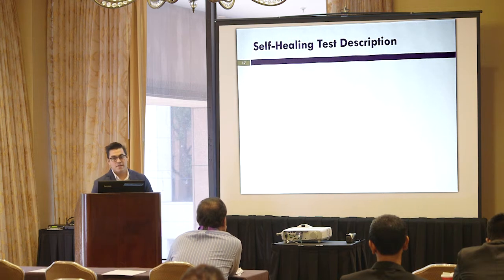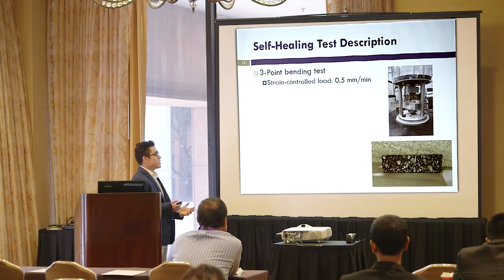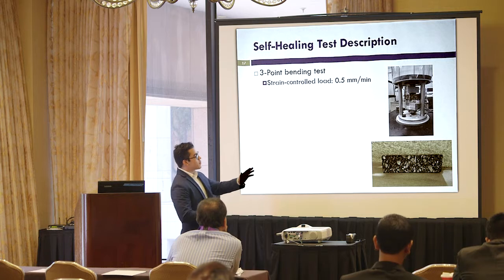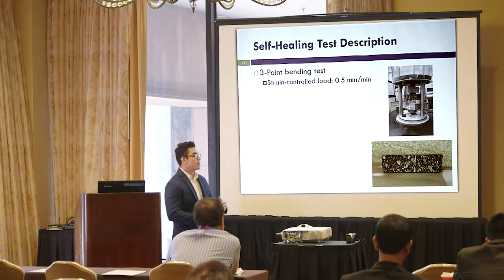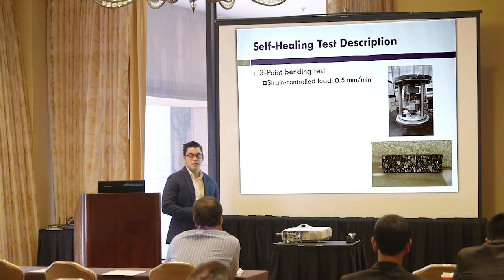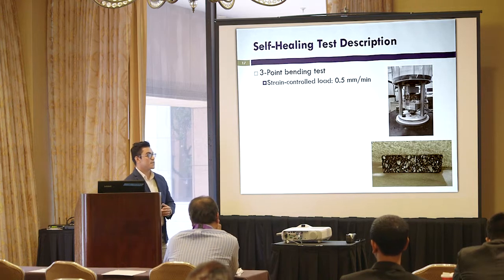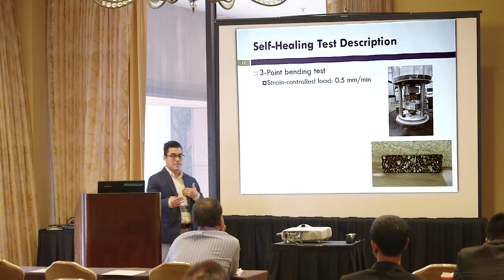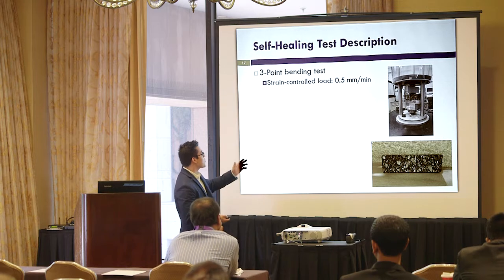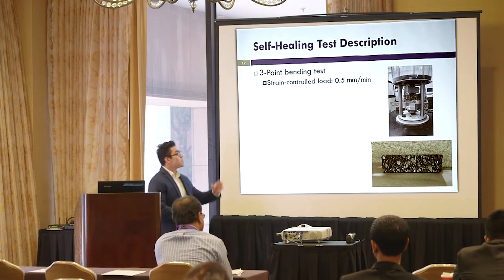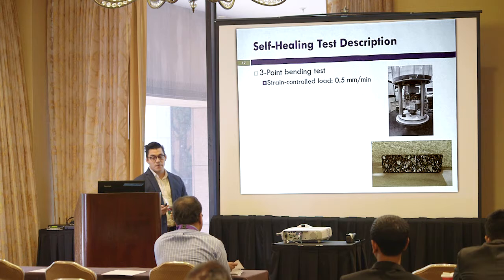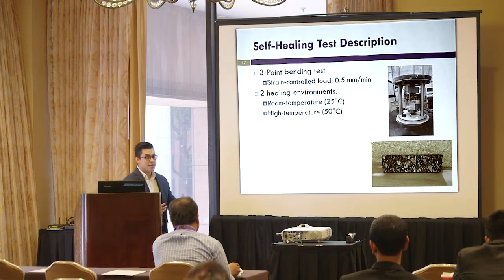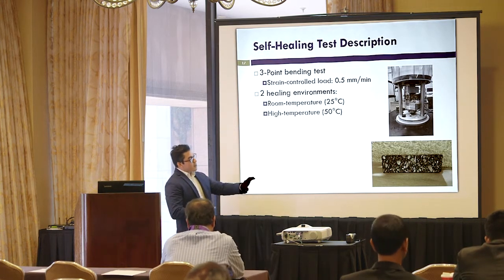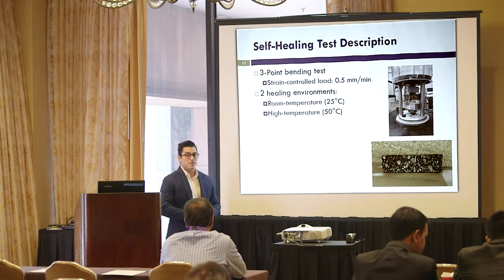Now I'm going to explain the self-healing test. So basically, we are performing a three-point bending test on rectangular specimens. The size of the specimen is 4 by 4 by 16 centimeters, and we use a strain control load of 0.5 millimeters per minute. And the idea is to perform these three-point bending tests to induce a crack on the bottom of the specimen,